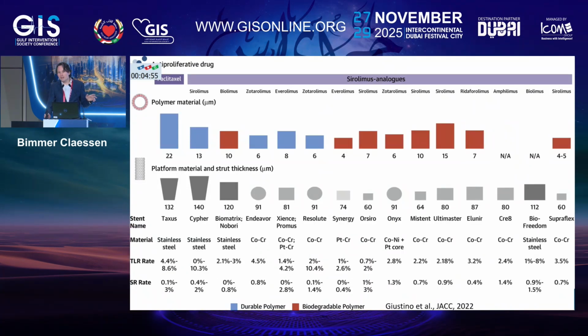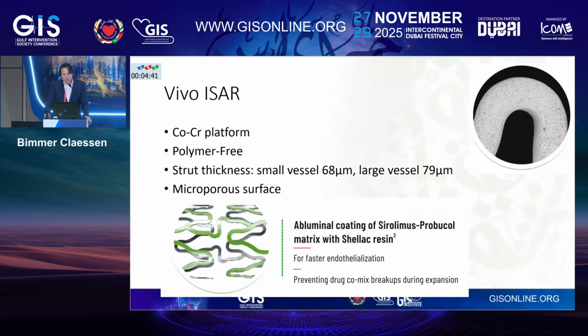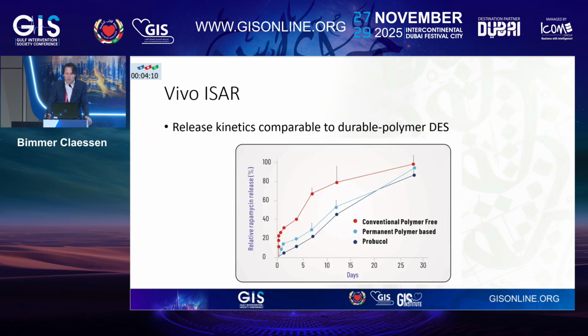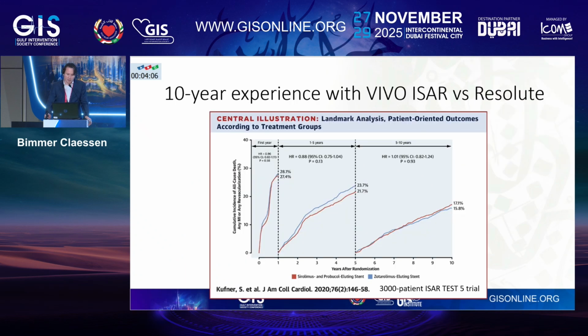This is a kind of incomplete overview of currently available drug-eluting stents. You can see there's many differences in the types of polymers, being biodegradable, permanent, or even absent polymers, the differences in strut thickness. One stent that I would like to point out as well is the Vivo ISAR stent, which is on a cobalt chromium platform. It's polymer-free. It has a strut thickness for the small vessel sizes of 68 microns, so it's a thin strut stent, and a large vessel size of 79 microns. A microporous surface and coated only on the abluminal side with a sirolimus Probucol matrix in a shellac resin. This allows for fast endothelialization because there's nothing on the vascular side of this stent, the luminal side, but it still has release kinetics that are comparable to durable polymer drug-eluting stents.